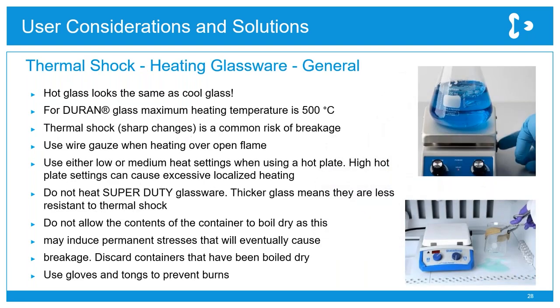So some general tips for heating glassware now. Number one, hot glassware looks the same as cooled glassware, so it's really important not to touch it, and we should be using protective gloves as well. So typically borosilicate glass can be heated up to 500 degrees. But this might be limited by any accessories like a plastic cap, for example.